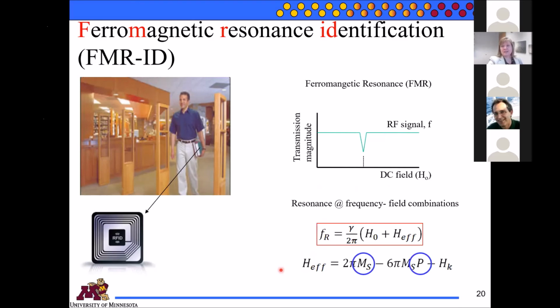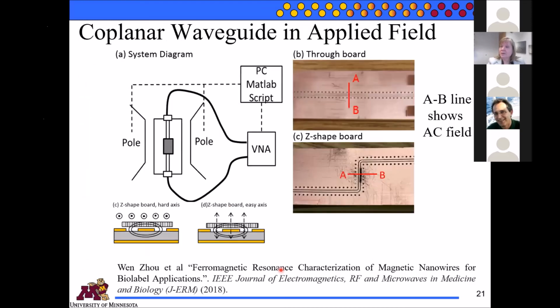And Ms and the porosity, if you're actually going to design these wires to not be single wires: a single wire would have a porosity of 0, and a porosity of 1 would mean you have a film. So we're able to dial in effective fields between single wires, so a shape anisotropy like such, and a shape anisotropy of the film. So here's what our measurements look like. At the moment, we're just using coplanar waveguides, so we can do a nice sweep, but there are other ways to try to measure specific signatures.